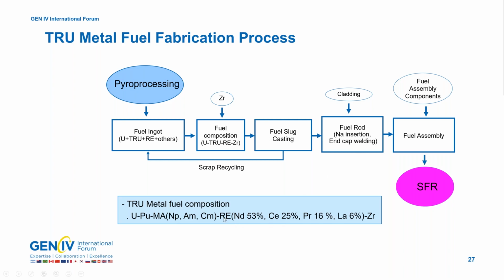In this TRU ingot, there are some impurities of rare earth elements, about four rare earth elements in their typical composition ratio, and these rare earths have similar electrochemical characteristics to the minor actinides. So they come together with the minor actinides. So we need to take care of these rare earths during the fabrication and also in irradiation behavior.